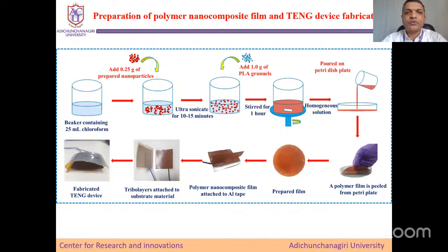Once we have nanoparticles, we can fabricate the nanocomposite by extrusion or by solvent casting. Extrusion is, of course, eco-friendly, but for the purpose of a nano device, we need a very small device, so we have opted for solvent casting. In a beaker, you take chloroform. Polylactic acid is dissolved in chloroform, and then through ultrasonication we dispersed ZnFe2O4, then dried, and poured it onto a petri dish to get the film.